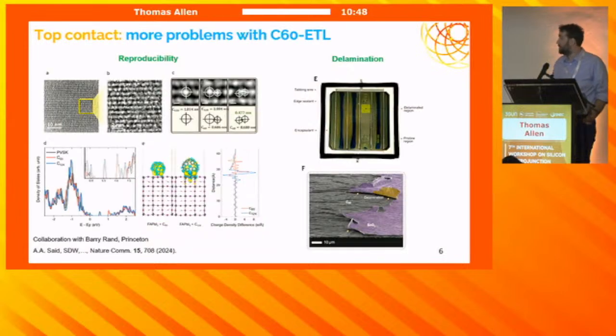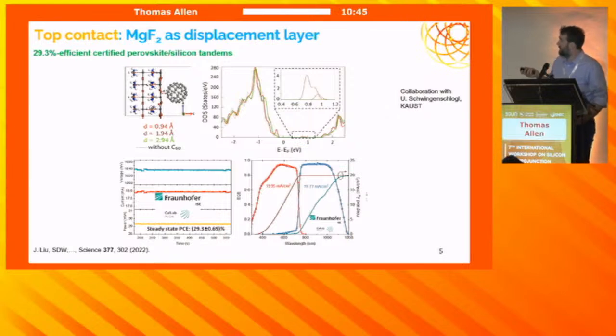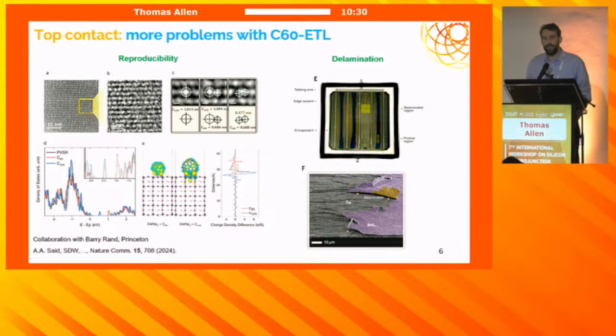But C60 has other problems. Not only the gap states, but you can see here in the EQE, a lot of this loss in the blue response is related to very strong absorption within the C60. So C60 is not good in terms of recombination, it's not good in terms of optics, it's not good in terms of reproducibility. And so here is a work from a postdoc in our group, Ahmed, where he looked at the reliability of the C60 process after repeated thermal cycling, so repeated evaporation processes using the same C60 source, showing a steady degradation with increasing evaporations of the C60 source.